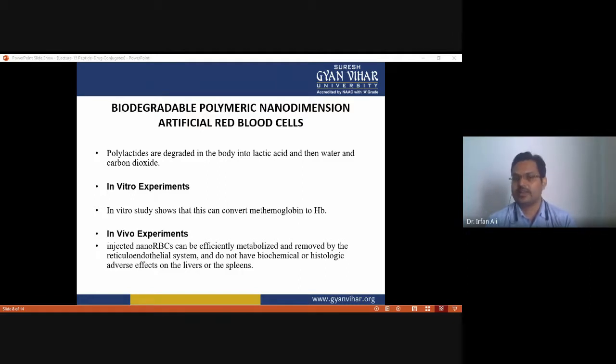The rats received one of the following infusions: nano RBC in Ringer lactate, SF hemoglobin, polyhemoglobin, or autologous red whole blood. Blood samples for biochemical analysis were taken before infusion and on days 1, 7, and 21 after infusion. Rats were killed on day 21, and the kidney, liver, and spleen were excised for histological examination.